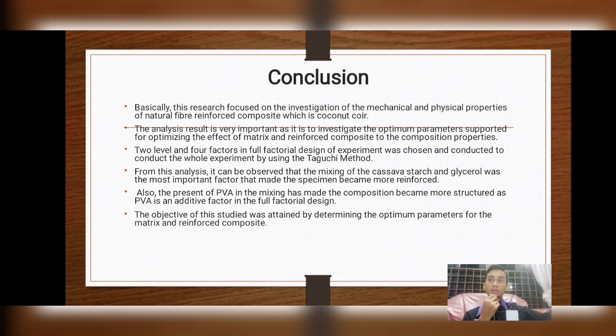And from this analysis, it can be observed that the mixing of cassava starch and glycerol was the most important factor that made the specimen more reinforced. Also, the presence of PVA in the mixing has made the composition more structured, as PVA is an additive factor in the full factorial design. Okay, the objective of this study was attained and completed by determining the optimal parameters for the matrix and the reinforced composite. Okay, that's all from me.